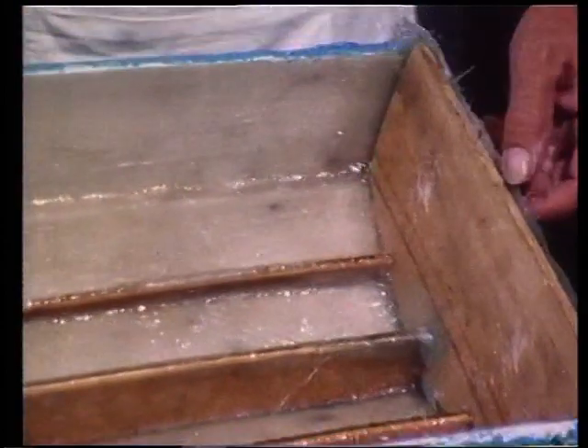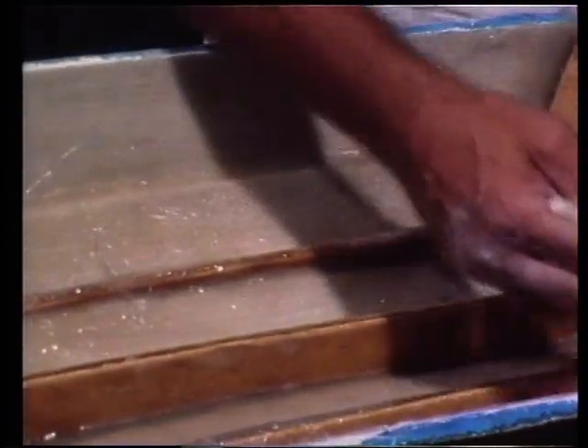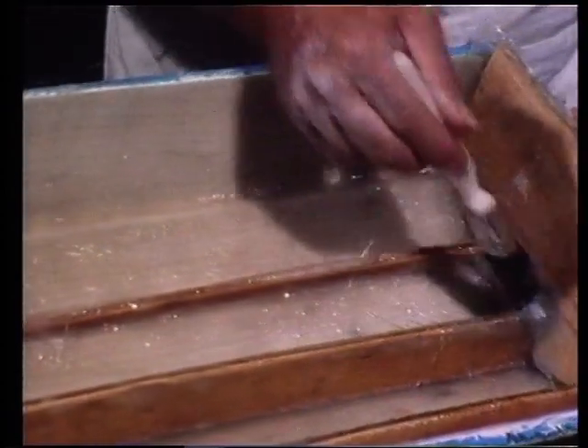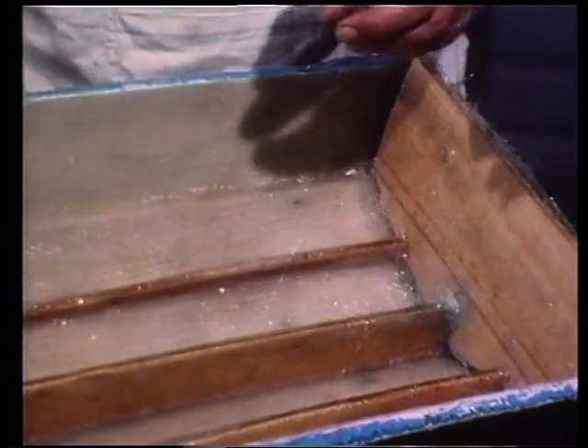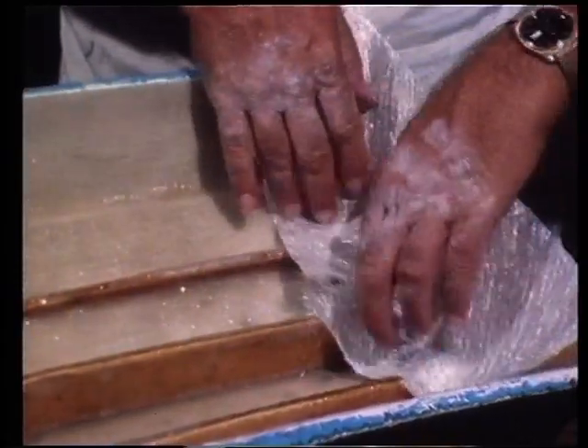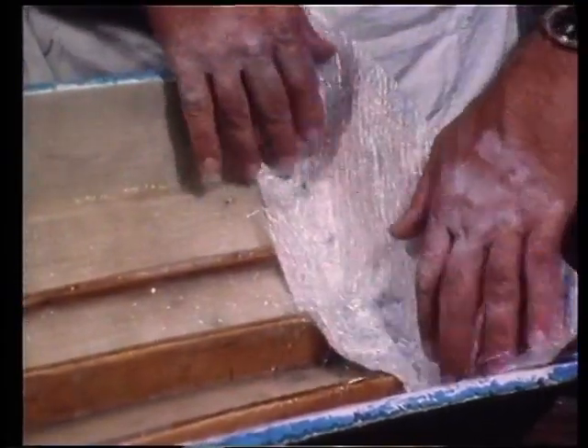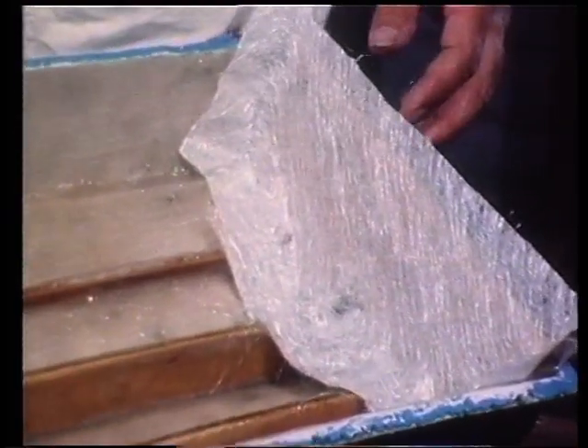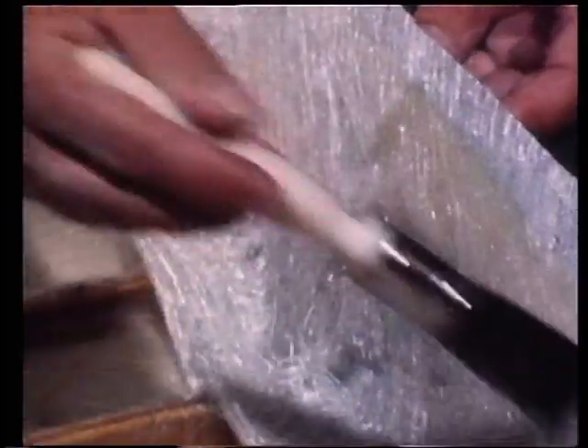Now, I'll just remove the clamps that hold the transom core in, and of course that is well and truly adhered to that fiberglass that we laid down underneath, and we put our final layers of glass over the top of it. Now, in this case I'll just put one in, but again, the transom is the most highly stressed part of the boat, particularly of course if it's a power boat, so you could use up to another 3 or perhaps 4 layers over the top of that in a full-size boat.